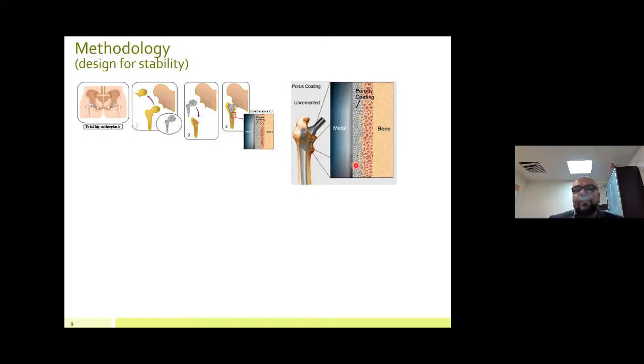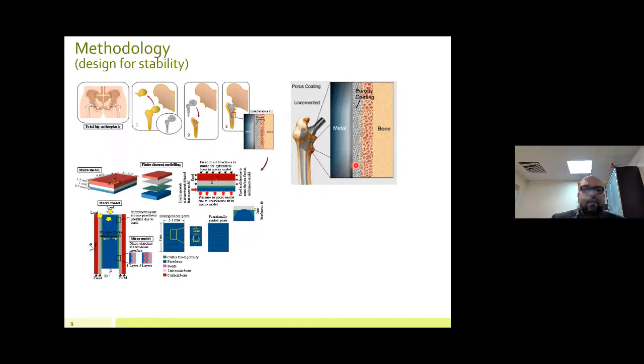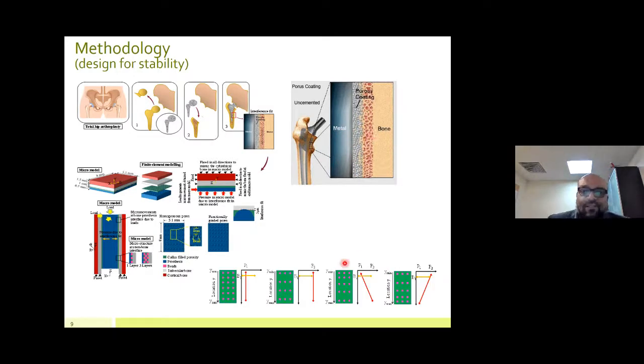So we want to bring this one step forward, and we want to design the way we do the coating, and that is through the introduction of beads, arrangements of pores or beads on the stem to improve the anchorage between the metal implant and the bone. So we played with various combinations on how we can arrange the pores or the beads on the outer surface of the implant and see which of these configurations allow better bone growth, which in return improves the stability.